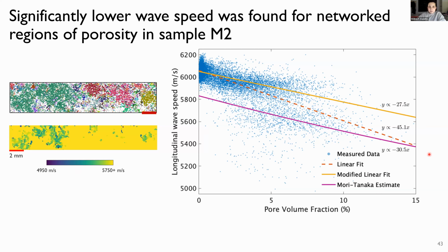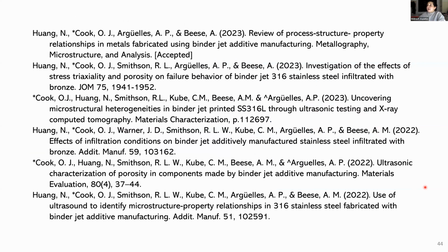Now, obviously, there are some simplifications in this analysis. The Mori-Tanaka model is still assuming static properties, and so there are inherent assumptions there. But there are reports that the effective modulus in a static problem is going to be more significantly affected if your porosity is interconnected versus if you have porosity that is evenly distributed. So this was kind of exciting to see that we're seeing that reflection in our ultrasonic data as well.